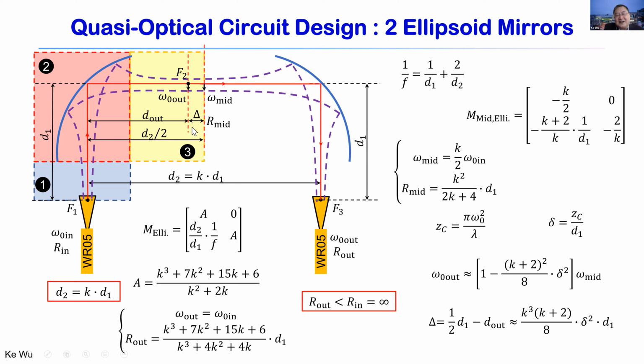So this delta is very tricky for the measurement. We want delta as small as possible to make sure that the measurement can be accurate. But at the same time, this also gives us a restriction on how much thickness of the material under test we can handle. Of course, we consider thin film and thick film types of structures.